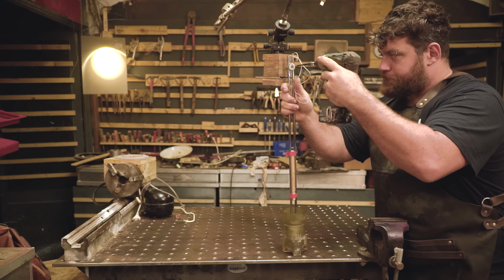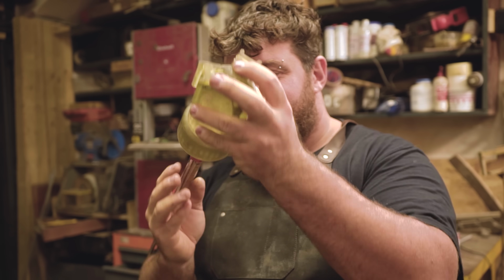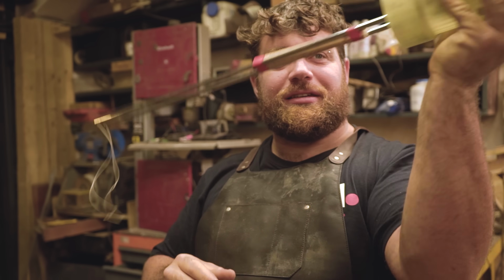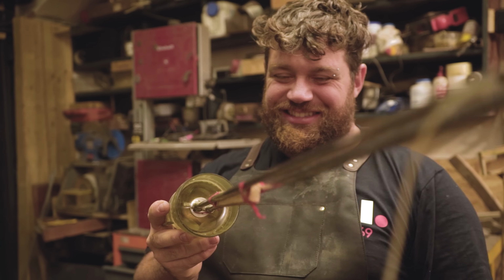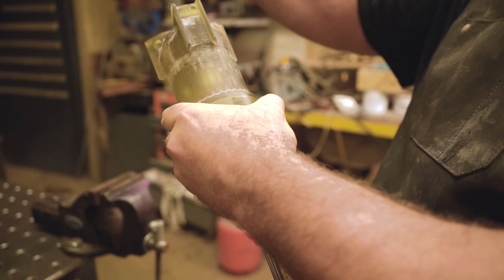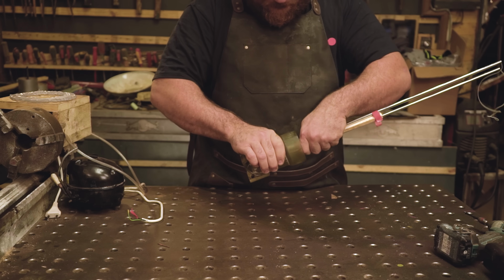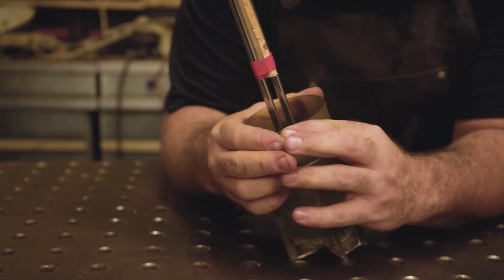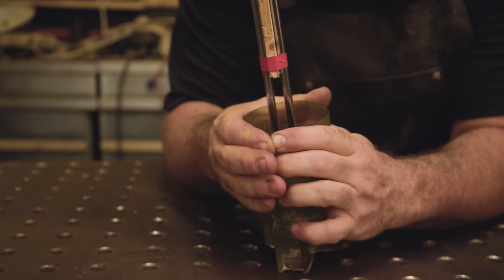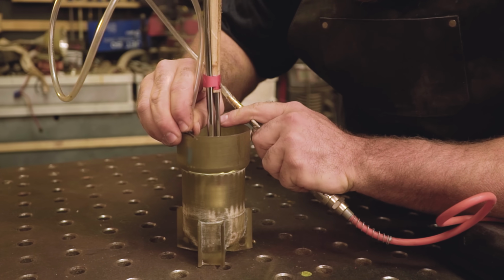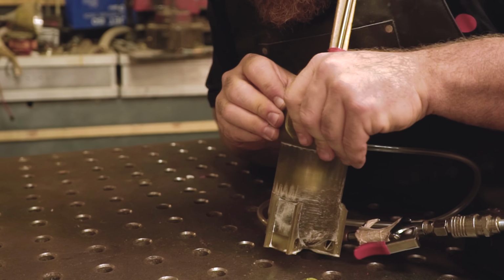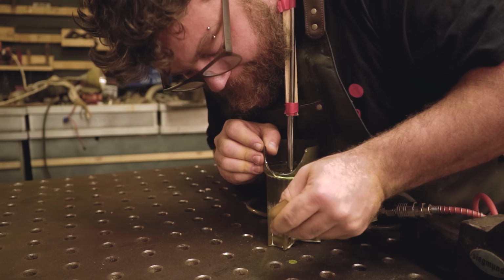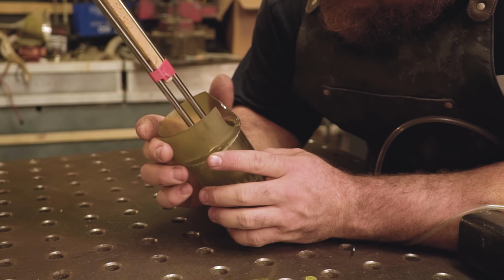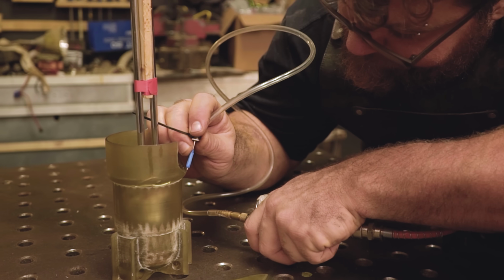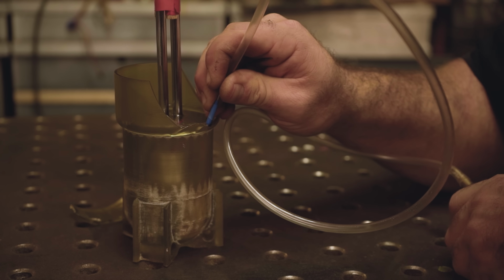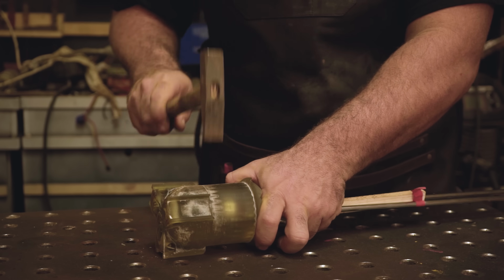And this unfortunately took quite some time. Removing it, just pulling the two brass tubes, is impossible because they are glued inside. I tried as well to squish the container, but everything seems stuck. I then realized I can use some compressed air, with a very small needle, to push some air around the mold. But here as well I'm having so much trouble, I decided to destroy the mold and try to push in the air here. But even this method that usually works doesn't work in this case.